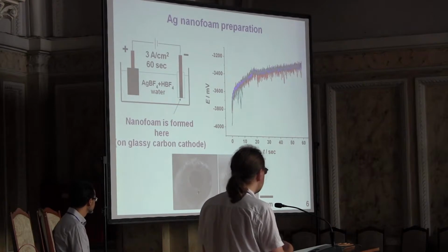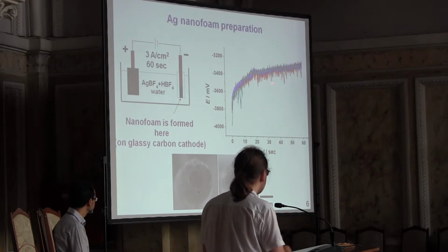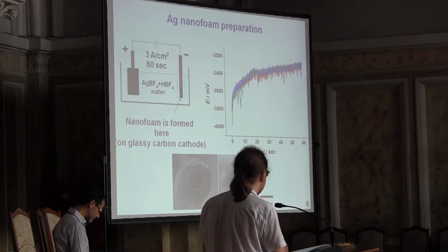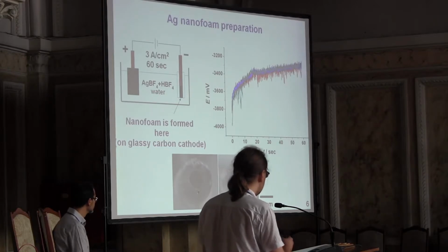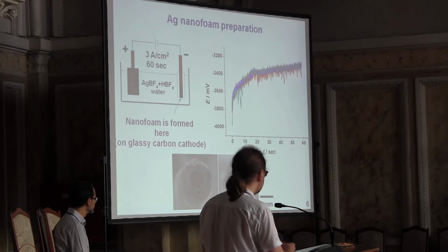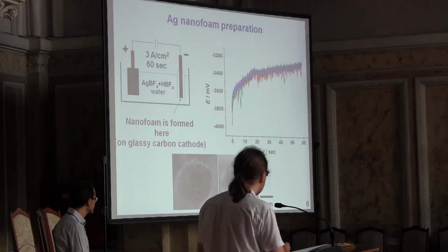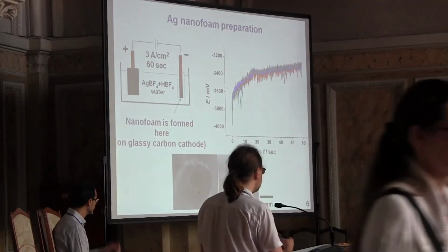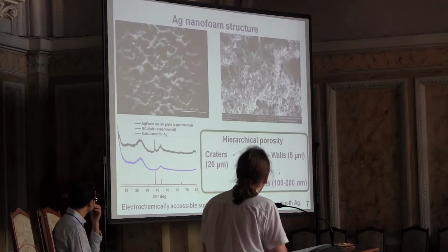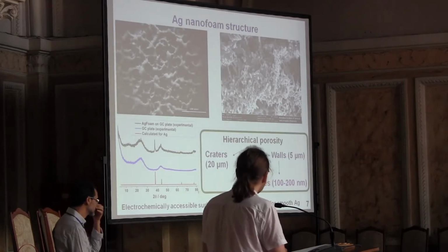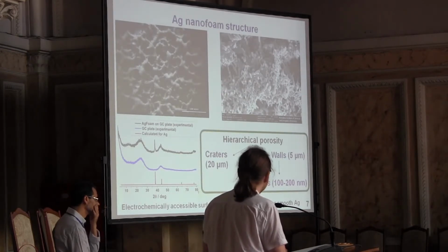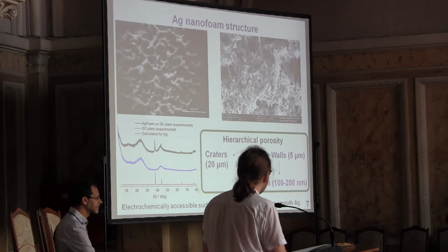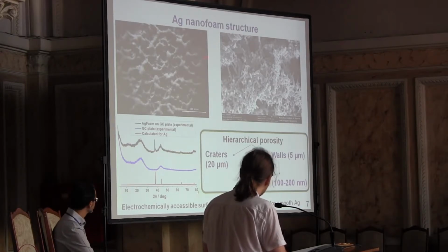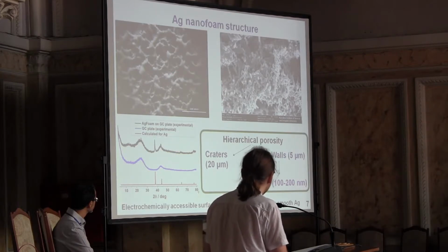manifested fast repeat oscillations of potential with time, which can be attributed to formation and elimination of hydrogen bubbles serving as a soft template in this process. However, trend lines of the potentials demonstrated high reproducibility. The structure of the resulting nanofoam was investigated by a series of methods. First of all, optical and scanning electron microscopy, cyclic voltammetry, and X-ray diffraction.